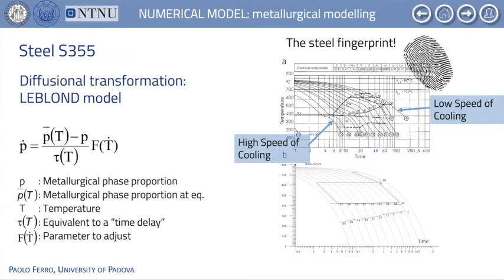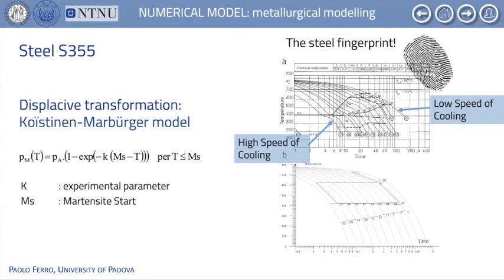The material investigated in this work is the S355 structural steel, whose solid-state transformations are modeled using the Leblond-Devaux model when considering diffusional transformations, and the Koistinen-Marburger model when dealing with displacive transformations, such as the martensitic transformation. Model parameters, of course, are calibrated by referring to the experimental CCT curves of the steel, as shown on the right side of this slide.